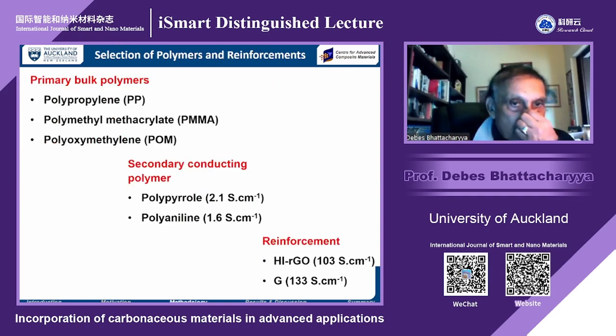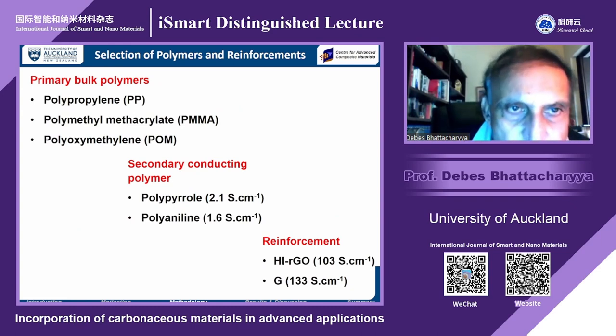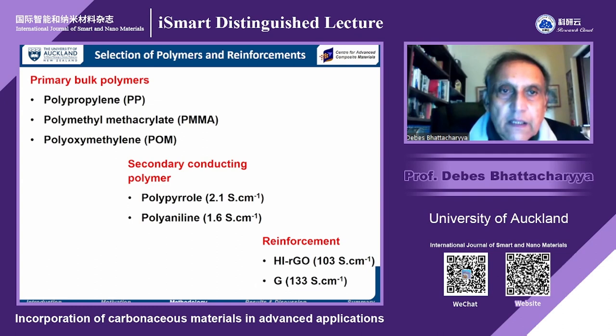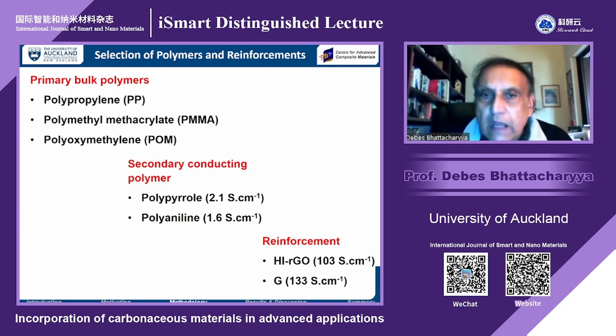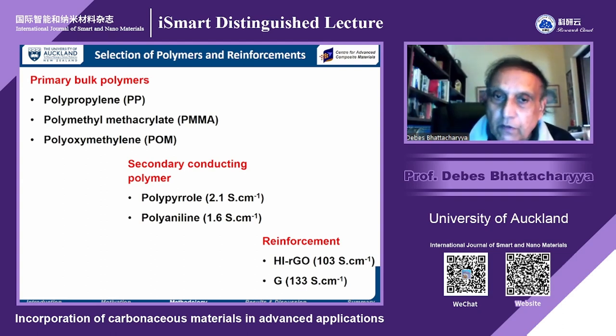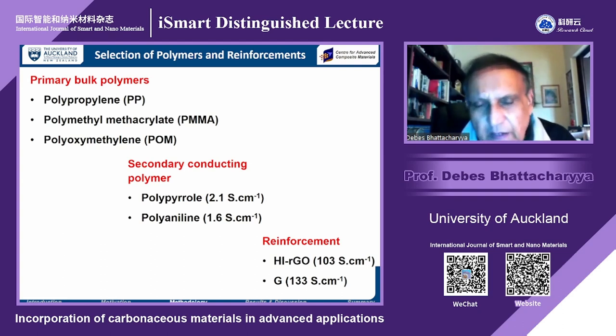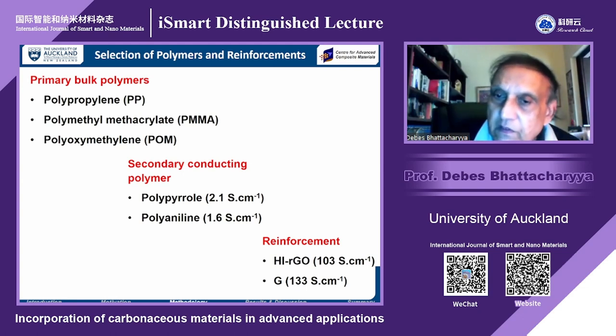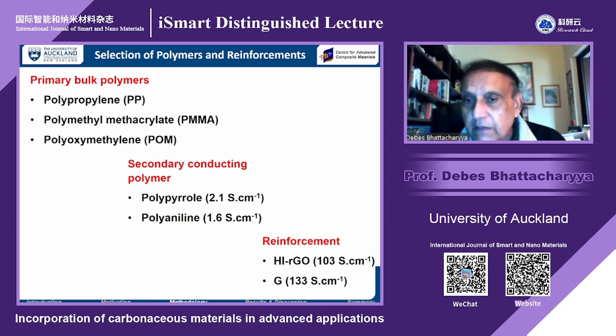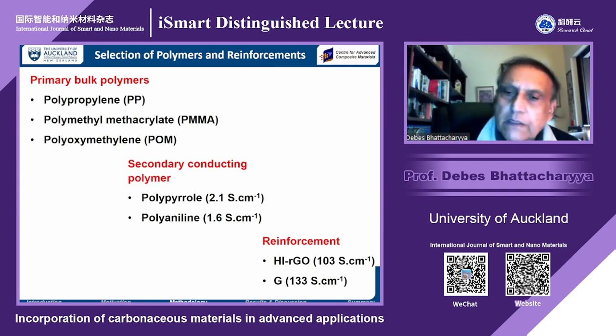So essentially, if we write in steps, you have primary bulk polymers, could be polypropylene, polymethyl methacrylate PMMA or polyoxymethylene POM. That's the primary polymer, in large quantity. Secondary is a conducting polymer, in smaller amount, could be polypyrrole or polyaniline. Polypyrrole is fairly expensive, so you might sometimes go for polyaniline, but polypyrrole gives you much better results. And then the reinforcement you can bring in with RGO or, in fact, graphene.